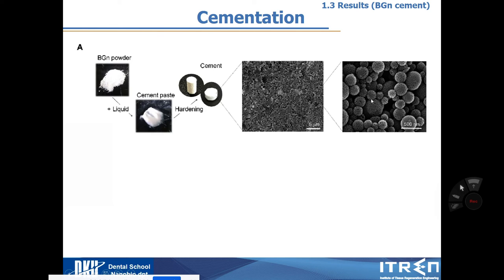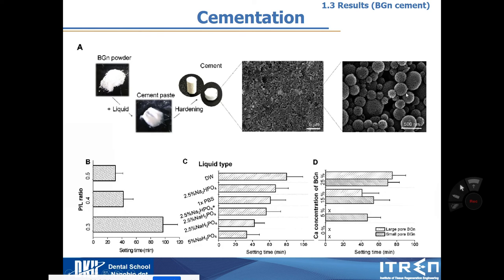And when you look at more nanoparticle, you can see like this. And then I want to determine the powder liquid ratio from 0.3 to 0.5, and maybe this 0.4 looks optimal, which has a lower setting time. And when you mix the liquid and powder, I can get more viscosity to apply in dental pulp. And then as a liquid, there are several candidates. And then I chose this NaH2PO4 2.5%, which has the lowest setting time.